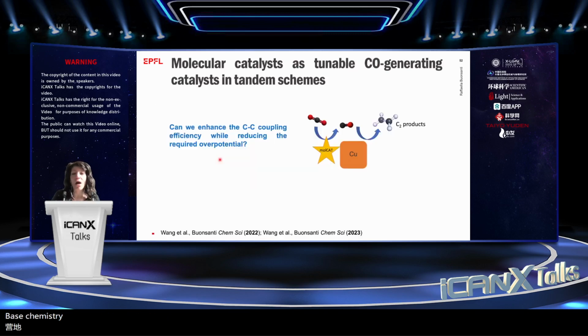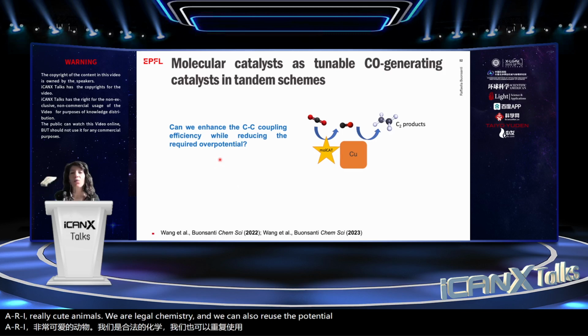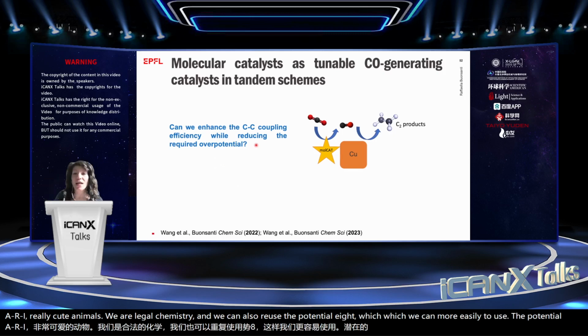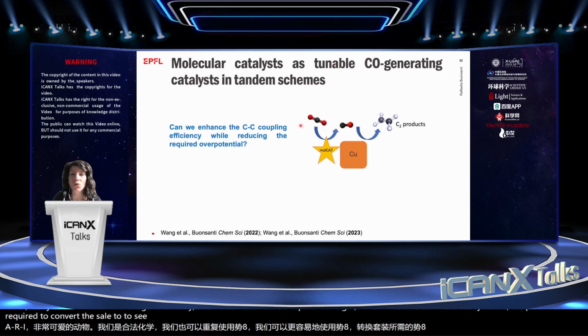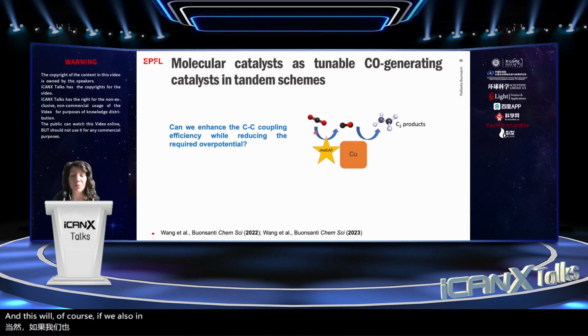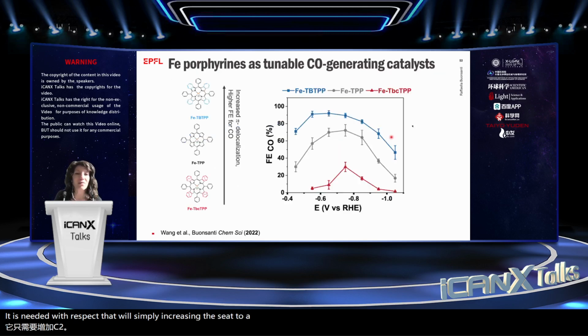And I also would like to add that this solution-based chemistry also enables us to go beyond metals and to start maybe combining particles with molecular catalysts. Why is this important? Because molecular catalysts are highly tunable via ligand chemistry. And we can also more easily reduce the potential that is required to convert CO2 to CO. And this will, of course, be also an improvement that is needed with respect to simply increasing the C2 selectivity. And so what we did here was also to start tuning, via ligand chemistry, the performance of these iron porphyrin molecular catalysts.